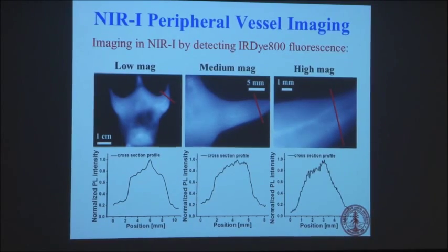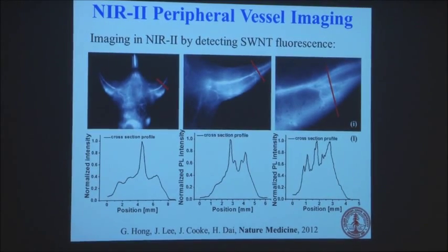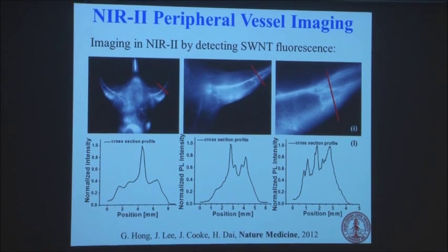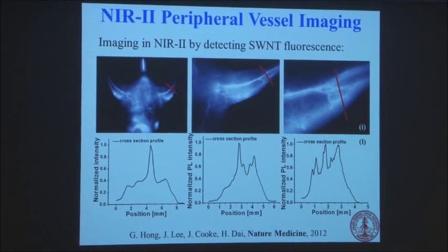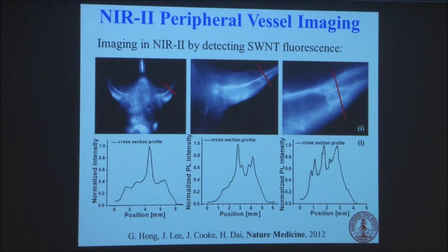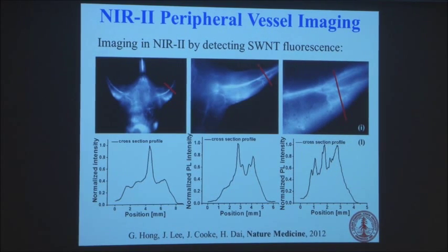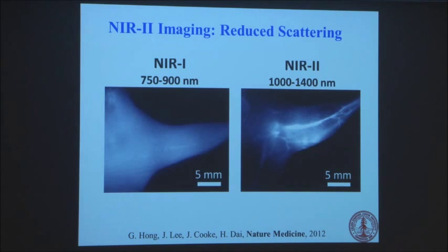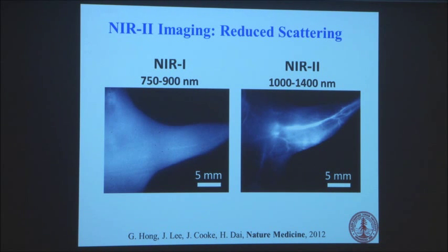Okay, now you can actually really see these vessels quite well and see their structure and utilize this reduced scattering effect, okay, to better resolve things in a body. And ideally, you know, optical imaging is limited by the diffraction limit, okay, about half of the wavelength of light. So that would be the most ideal case, but in this case, you still have some scattering, which is still causing this broadening effect, but at least we're now doing much better than before. So here's a side-by-side comparison, which can give you a sense of what the difference is. Okay, the difference is quite obvious to me.